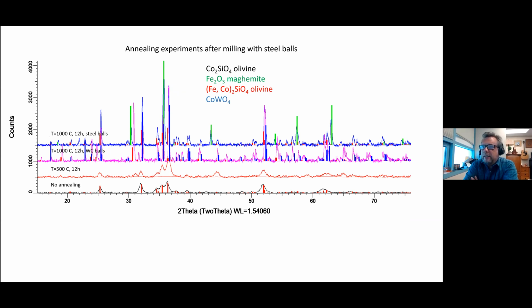And we tried annealing the product. We already had the cobalt olivine just after completing the milling experiment. But by annealing, we could make it more crystalline. We could control the grain size better. We could grow the grain size to larger sizes if this was desirable. But we noticed that because of these impurities, because of having tungsten carbide or iron in our sample, on annealing we get chemical reactions. So a little bit of our product gets transformed into cobalt tungstate, or in case of presence of iron, we get a little bit of contamination with iron oxide phases, particularly maghemite.